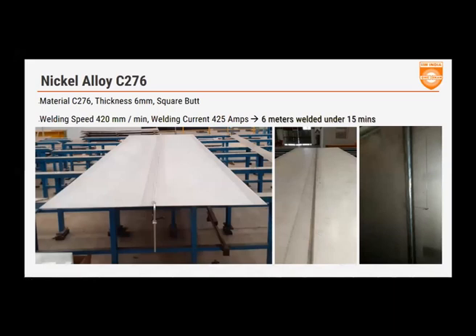This is nickel alloy C276, 6 millimeter thick, 6 meter long plates. This is the pre-tacked version where it was not welded. This was put onto a long seamer with a hydraulic clamping station. And then this was welded at speeds of about 400 millimeters a minute. They welded the 6 meter long joint, 6 mm thick, in under 15 minutes.